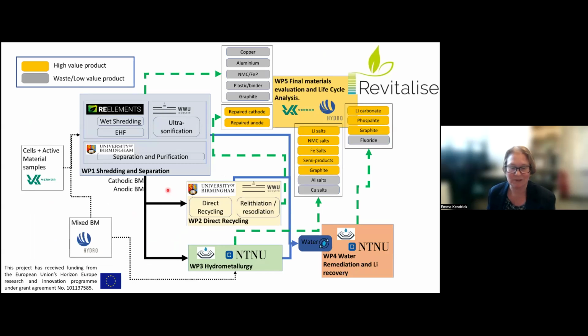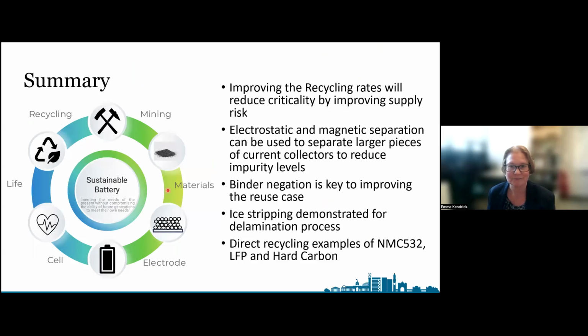We are looking at some of the separation and direct recycling of different lithium and sodium-ion materials. Just to summarize, improving the recycling rates will reduce the criticality by improving supply risk. We've shown that we can use electrostatic and magnetic separation with large pieces of current collectors to reduce impurity levels in our black mass that we reclaim for direct recycling.